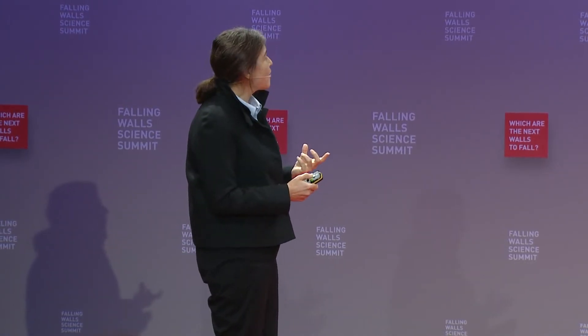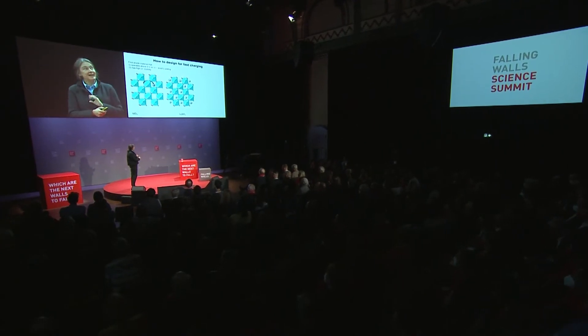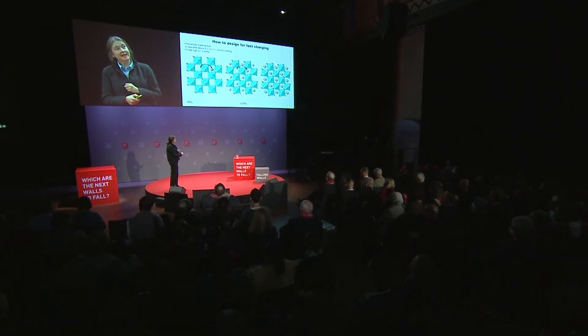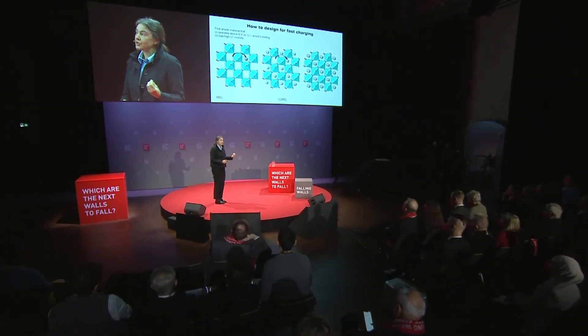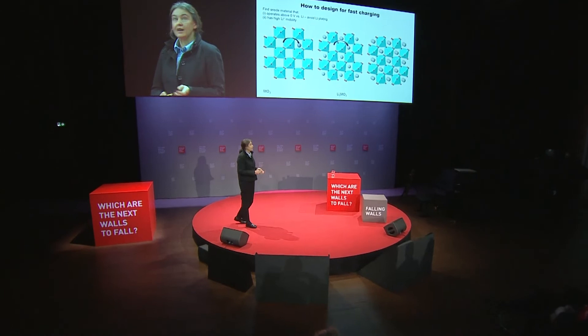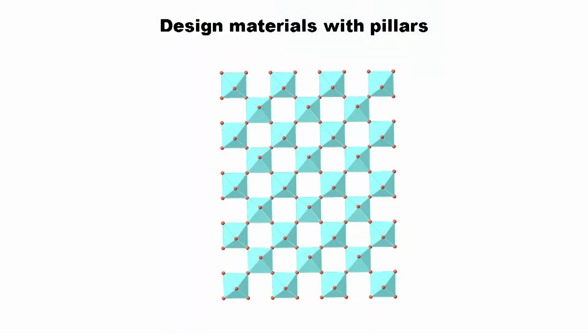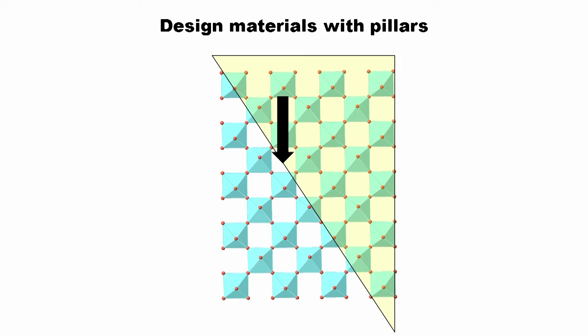There's one problem with perovskites: when I insert a lithium ion, I also insert an electron, and that changes the metal-oxygen distances. The structure rotates and clamps the lithium in place, giving very high resistance to lithium movement. What we did was take this structure and put pillars to hold it up, via something called a shear — removing oxygens and literally moving the layers together to form a column. A bit like a spinal fusion operation to limit mobility and prevent slipped discs.